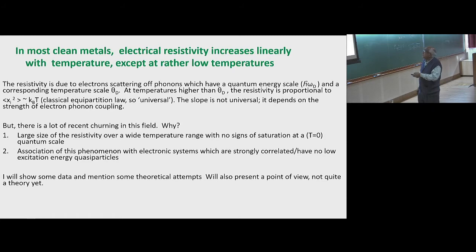The slope of this linear resistivity is not universal, but it depends on the strength of the electron-phonon coupling. But this is a very well-known thing. But then there has been a lot of excitement in this subject in the last 20 years. Why is that? That is partly because the size of the resistivity in many systems, which we have been studying, is extremely large. Not only is it large, it is large over a very wide range of temperatures.